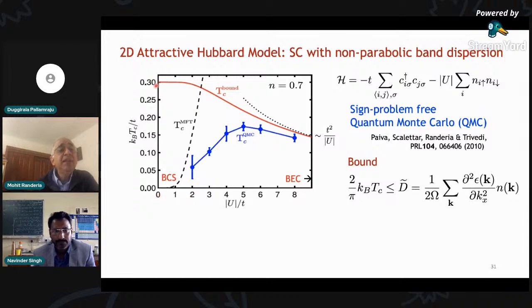And here I'm plotting TC scaled in units of the hopping matrix element versus the interaction strength. Again, for weak interactions, you expect a BCS transition. For strong interactions, you get tightly bound bosons, but their mass is very heavy because in order to hop, you must break and reconfigure. That's why TC goes like t squared over U.